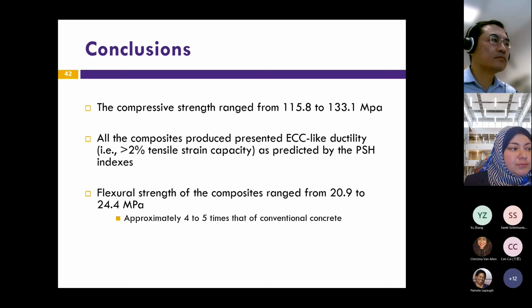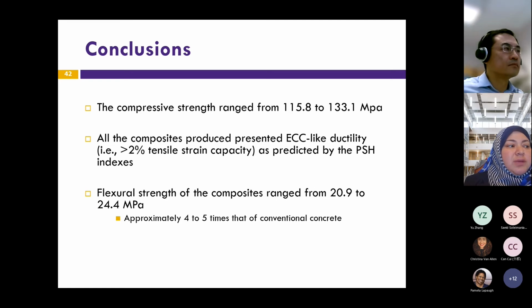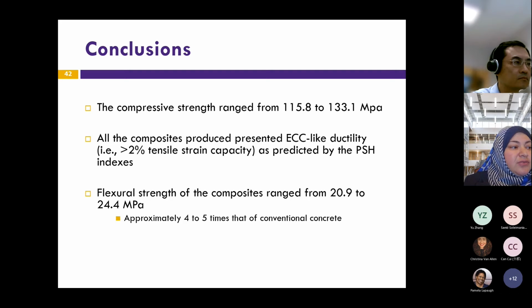So to conclude, we were able to design mixes that ranged between 115 to 133 megapascals. All the composites presented here had ECC-like ductility with more than 2% tensile strain capacity. And the flexural strength of the composite ranged from 20.9 to 24.4, which is 4 to 5 times that of regular concrete. So we were able to successfully design ultra-high performance ECC with local ingredients and at a much lower cost.